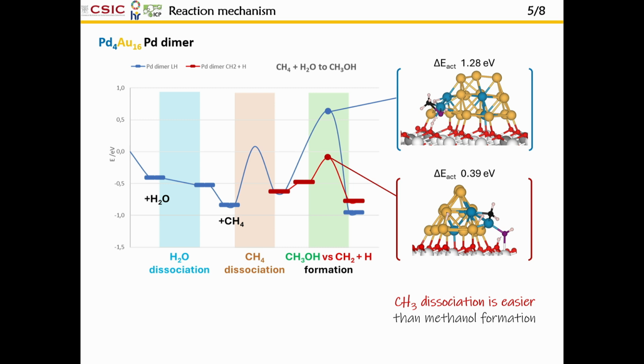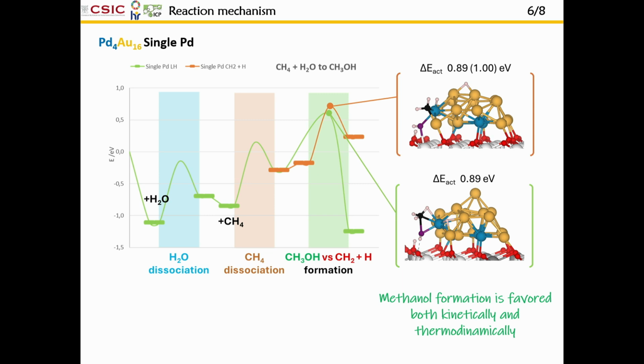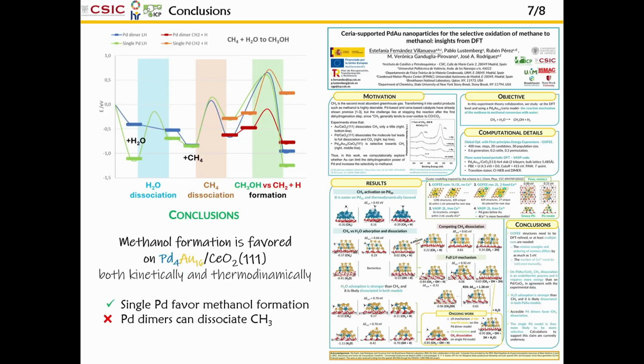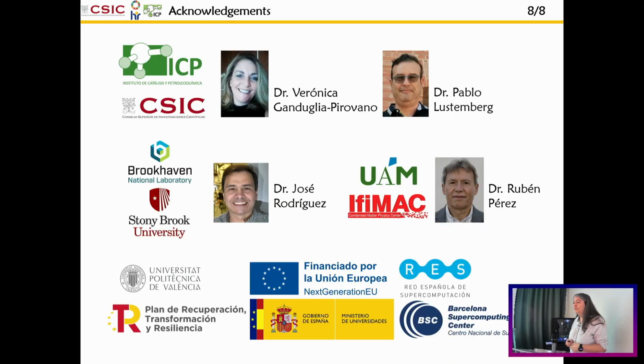that when you have this palladium dimer, you are able to stabilize this CH2 species, and therefore you are favoring the competing reaction, which is what you do not want. In contrast, when you have only one palladium atom, this becomes greatly unstabilized both kinetically and thermodynamically, and that's how you increase your selectivity to methanol. So I will be by my poster if you want to know more about this. And with that, I thank all my colleagues, the funding, and you all for your attention.